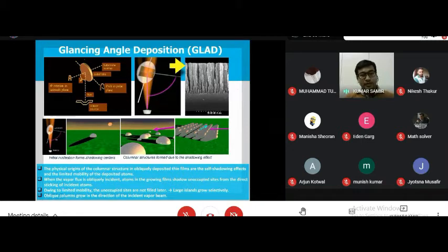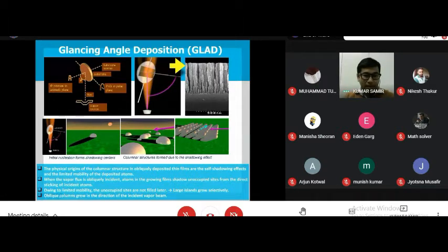Also, this substrate can rotate in both azimuth and polar planes so that we can control the film morphology. In simpler terms, during the initial growth, random nuclei form on the substrate due to the surface roughness, and some of the nuclei are larger than the smaller nuclei behind them. The larger ones receive maximum flux and grow in the direction of the incident flux because of the self-shadowing effect. Using this, we can form the nanocolumn very easily.